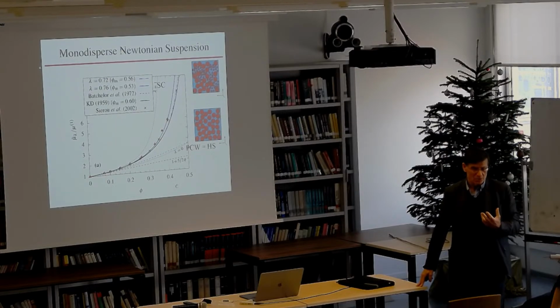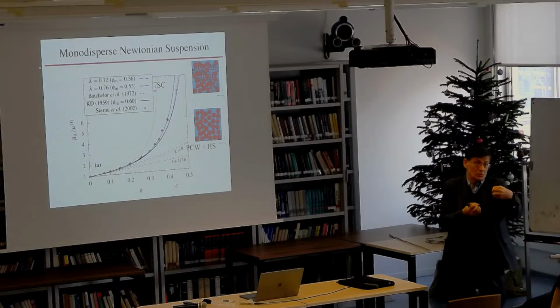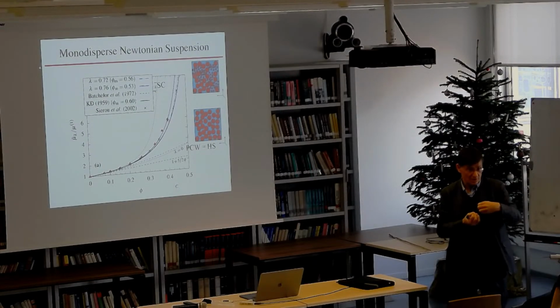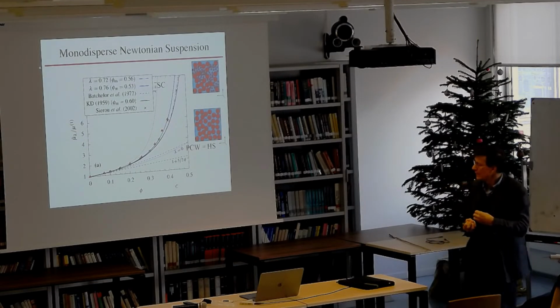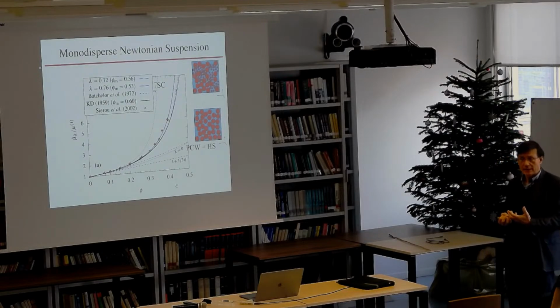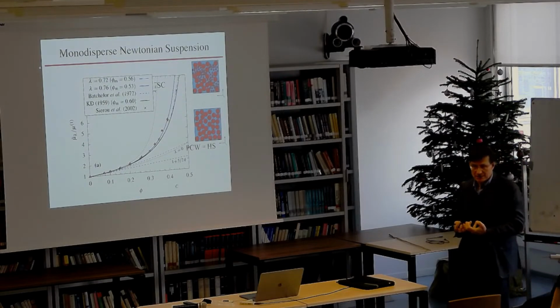So even just for the correction term to order volume fraction squared, you need to bring in information about the pair correlation function beyond the angular dependence, the radial dependence. This tells you, on average, how close the particles are, and about the interaction between the particles. But it's a very difficult calculation, and it assumes all the particles are the same size, and it's very difficult to generalize.